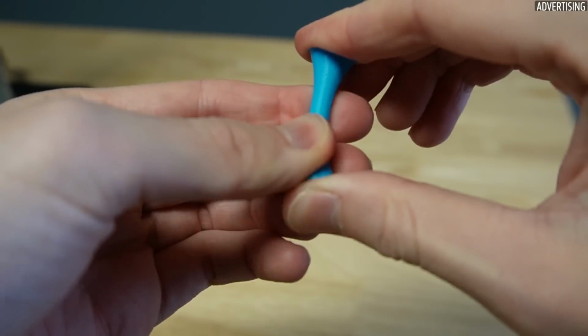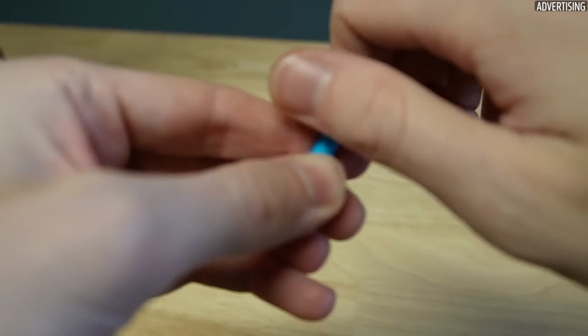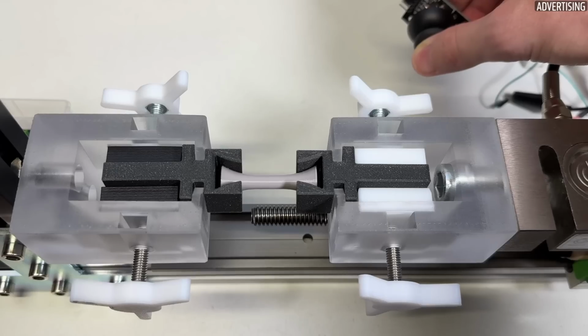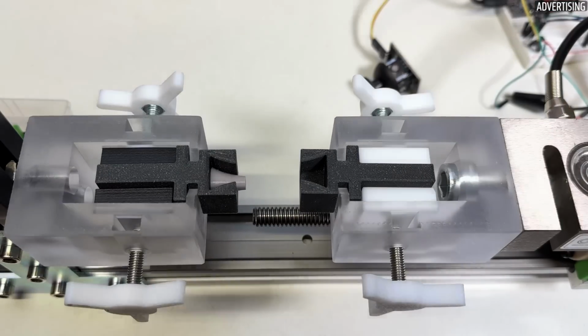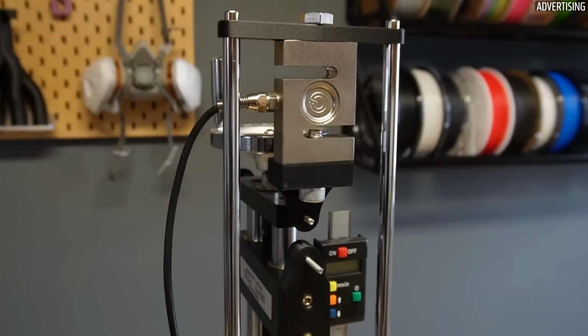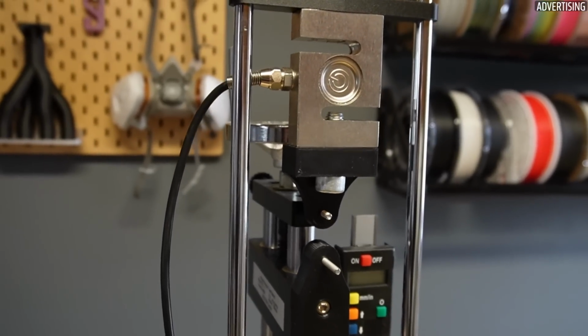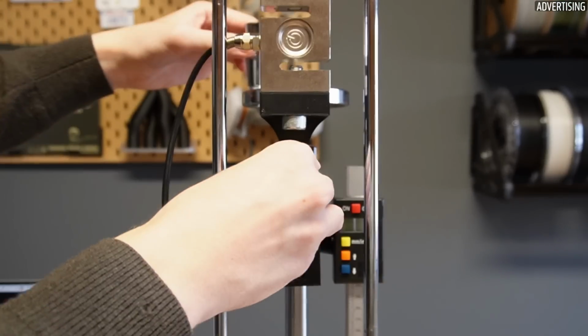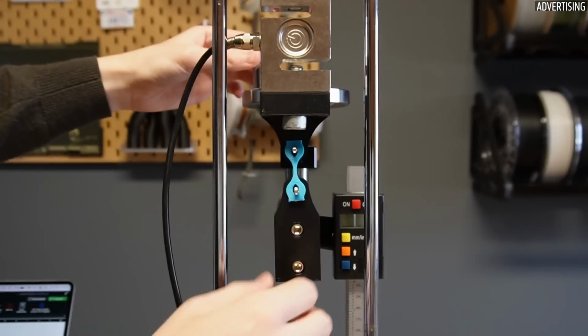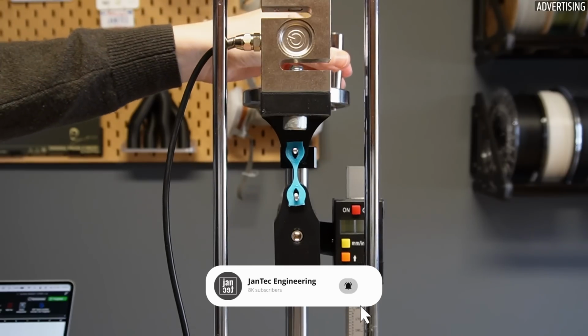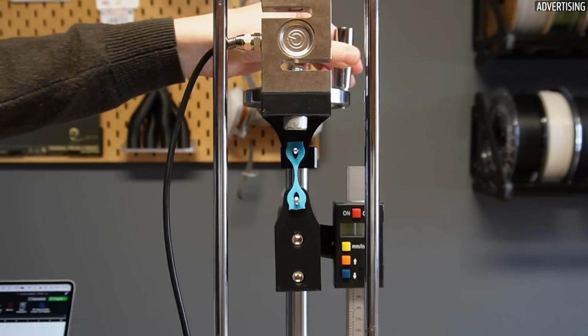More important is the layer adhesion, which can be examined with a tensile test. Since I'm currently rebuilding my motorized test stand, I had to rely on the old one with a hand crank. Here I came up with an average tensile strength of 20.3 megapascals, which is slightly worse than normal PLA, but better than materials such as ASA.